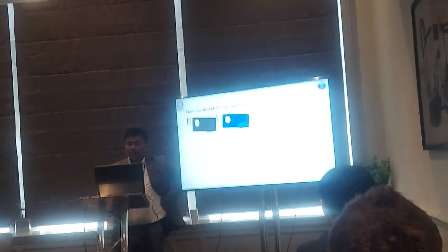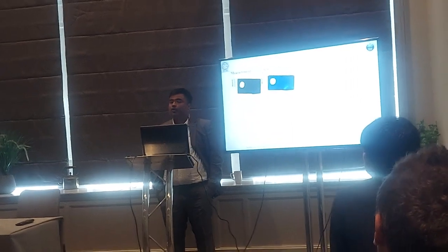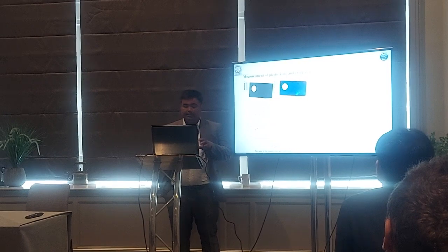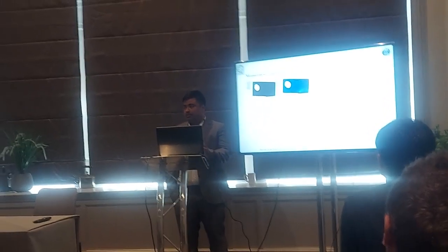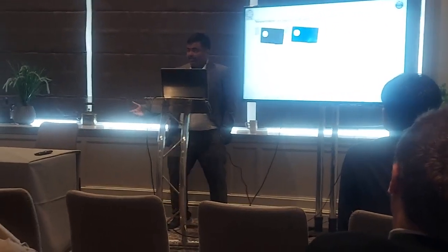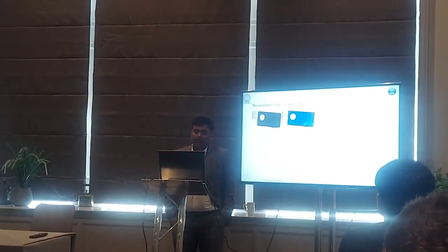For validation of this concept, whether I am wrong or right, I have done some simulation work. To ensure my result, I performed the simulation using the node release technique. With the help of the node release technique, I simulated the experimental results with da by dt, and with different steps I performed the test and found out the plastic zone size and the creep zone size.